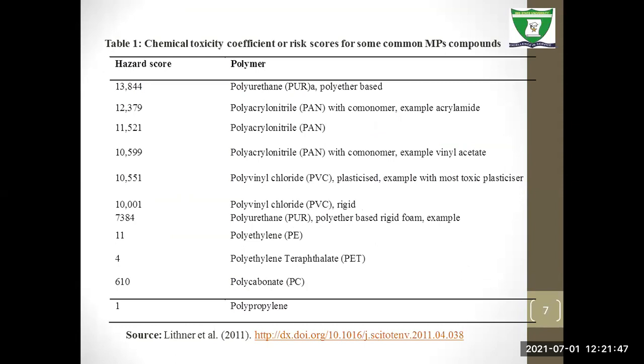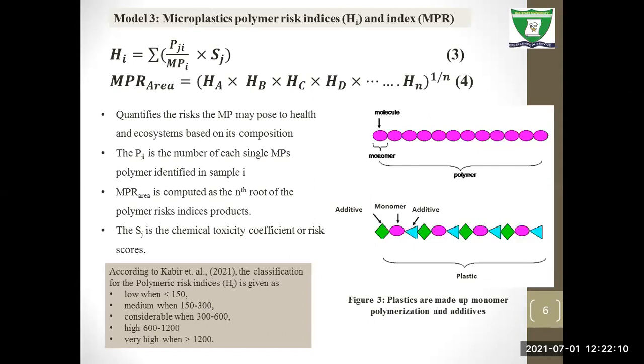These are some of the risk scores presented in this slide by Lithner et al. 2011. These risk scores are based on the toxicity level of the particular polymer. In the study of Lithner, up to 50 different polymer risk scores were presented. Those risk scores are multiplied by the PJI divided by the MPI to get the HI for that particular sample. Then you do this for the different polymers identified: for PP you calculate, for PET you calculate, for PVC you calculate. You have values for each of them, or you sum them together. Once you sum them, you have your HI, which is the summation of the individual polymers' quantity divided by the total quantity of microplastics identified, times the risk scores. That way you get your polymer risk index.